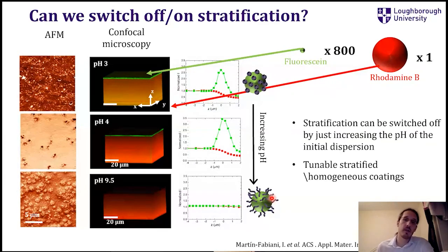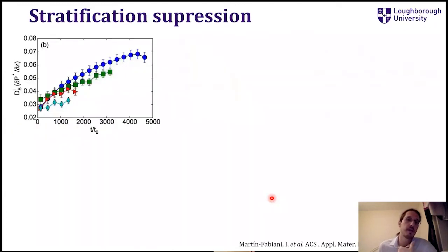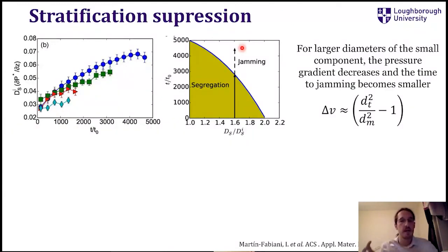The main reason is basically the jamming of the dispersion, which is when the particles cannot move anymore. That happens earlier when we have less space available. So when we have larger small particles, we have less space available initially, we have less time for drying, and therefore all those factors make this size segregation more difficult to happen. So we have somehow hindered the stratification, and we can just switch it on and off by changing the pH of the initial dispersion.